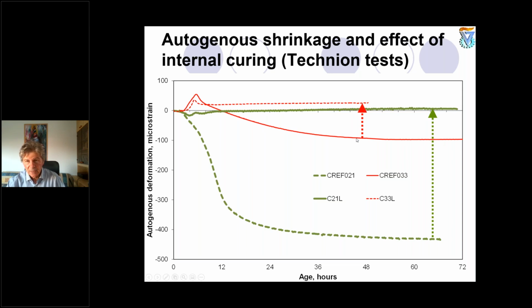how to compensate it? In both cases, we introduced lightweight aggregate. For example, here we succeeded to completely combat autogenous shrinkage, and here also. So this is kind of a plateau with maybe very small expansion in the very beginning. There is still some dispute among the scholars about the reason for this very small expansion, but this is not a problem. The problem is the shrinkage, because under shrinkage in restrained conditions the tensile stresses are generated, and concrete is not good under tension, as we know.